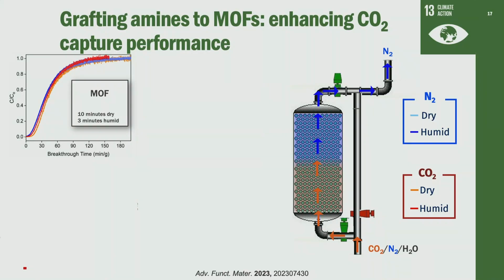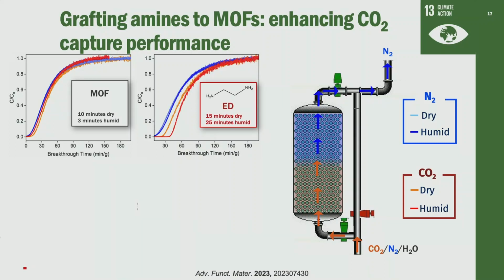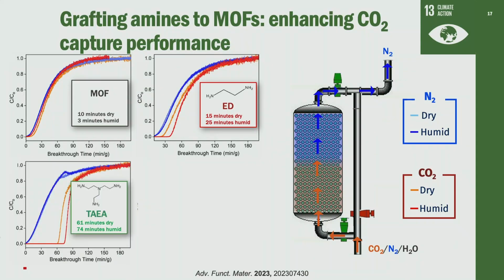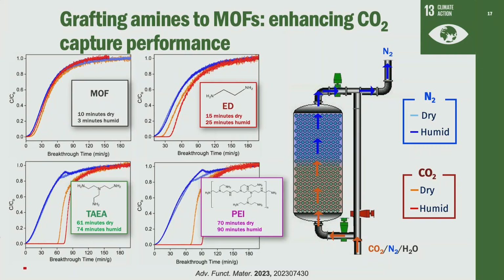conditions. You'll note that for the unmodified MOF, we only get breakthrough times of between 3 and 10 minutes, depending on how much water there is in the gas mixture. Now, when we modify this with amines, we've been able to significantly increase our breakthrough time already to 25 minutes in humid conditions. Again, here with this molecule, we see 74-minute increase, and then up to 90-minute separation time for the last one. So we've been able to improve it by a factor of 30 times just by altering the amines that we've put inside the material's pores.